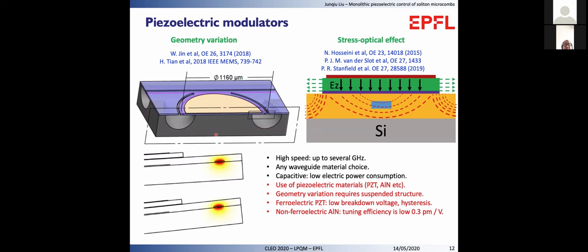Recently, it has been shown that piezoelectric materials are also useful to make optical modulators. The principle is based on geometry variation or the stress optical effects, and the latter is more often explored. By applying stress on the material, the refractive index changes in response to the applied stress. Piezoelectric modulators are high speed, up to several gigahertz, and can be applied on any material platform, not only silicon nitride. As piezoelectric modulators are capacitive, they consume low power.